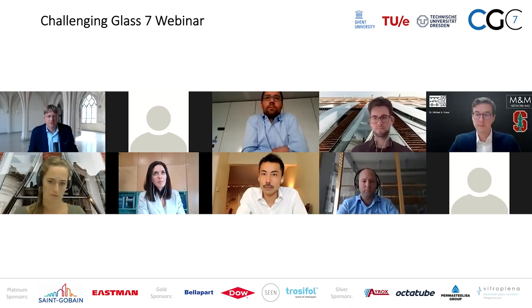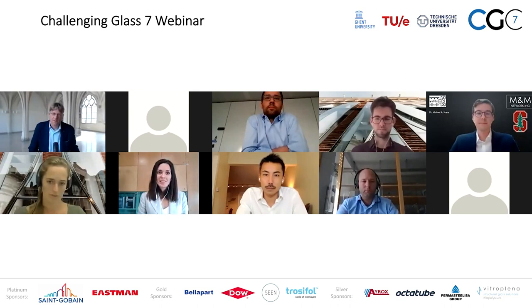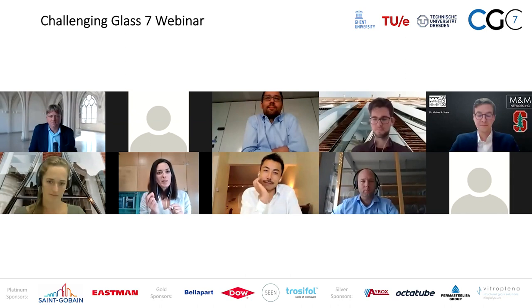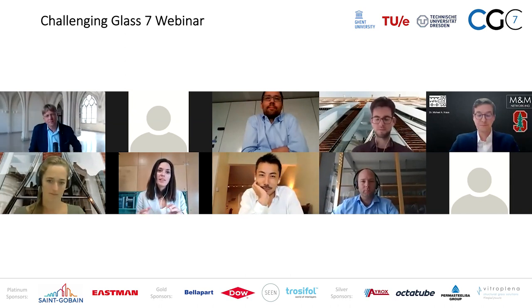So actually, yes, because we have been working with different glasses, we see also a different range of viscosities. That's why I was looking at Chikara's glass and I thought, this glass melts really nicely because it has a higher content of soda and a little bit of boron and some barium and other elements. And I thought these were also the glasses we had, that they were melting really nicely at a much lower temperature. Sometimes we were mixing a little bit of these glasses, the ones that had lead or barium in there, with a soda lime glass, and then that would drop the melting temperature a little bit.